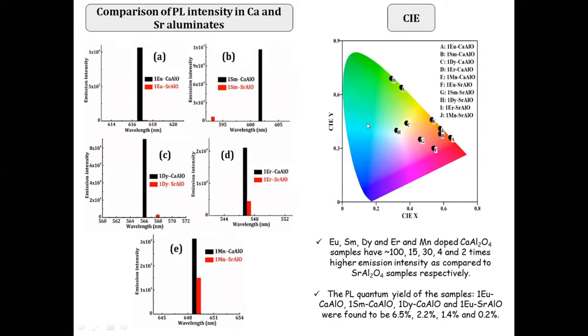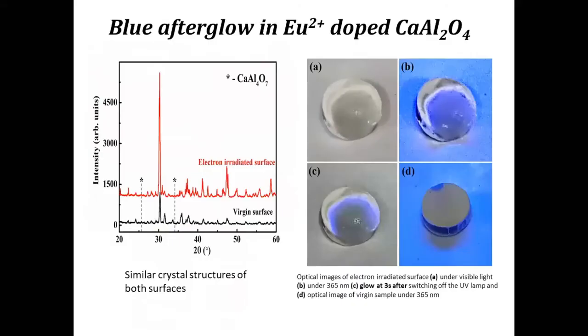So calcium aluminates are very good materials for red light and white light sources, and they are very cheap materials. You can prepare them using very low cost materials like aluminum oxide and calcium carbonate. If you bombard these samples with electron beams, then I can reduce europium 3+ to europium 2+, and then it shows blue light emission. We are very interested in blue light emitters because the phosphors which are emitting in the blue region are more scarce, they are more difficult to prepare. So I can convert europium 3+ to europium 2+, and I see blue light emission due to the electronic transitions of Eu2+ ions.